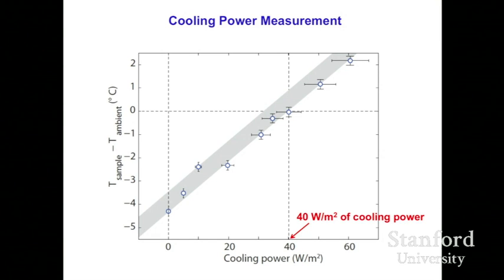This is a measurement of the equilibrium temperature. We've also done a cooling power measurement. And in this case, without putting any additional heat load, the sample will have a temperature on the order of 4 to 5 degrees below ambient. And as you put a heat load on, its temperature rises. And the amount of heat load that we need to put in order to bring the object back to the ambient air temperature is 40 watts per meter squared. And that's the cooling power we actually experimentally measure.